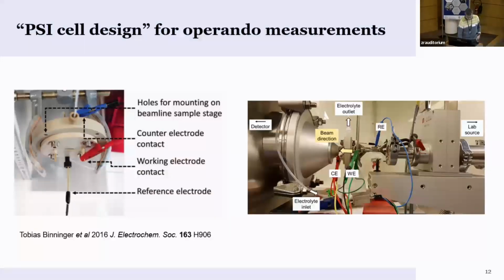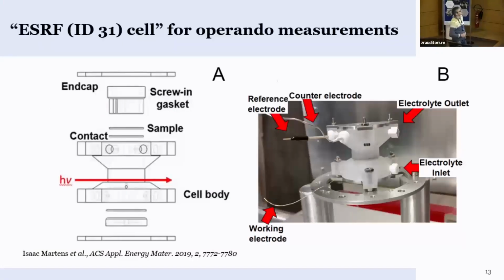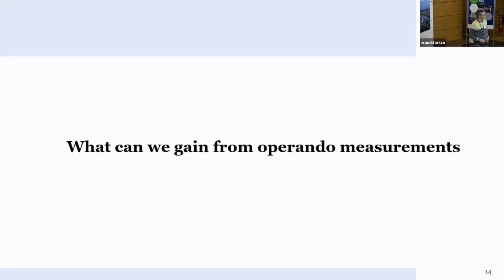and you can do the measurements while the beam is crossing your sample. It's a flow cell, or both are flow cells, and then there's a different design that was introduced here at the ID31, where you have the catalyst sample and the beam comes more or less parallel to the catalyst sample. And that has some advantages. As I will introduce later, one thing we are always fighting is the background correction of the carbon signal. And here, by changing the angle slightly, you can actually choose where you are in the sample. So you have that contrast, so that you can change the Z in the sample. So either you are in the catalyst layer or a little bit below, and that you can use for the background.